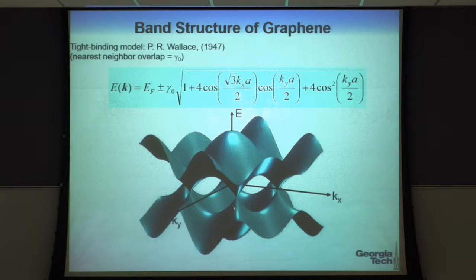And in fact, for graphene, that's where the charge neutrality point is. That is, all the bands are filled up to this point, the Dirac point, and then they're empty above that point. But you can dope graphene. You can put extra electrons in or take electrons out so that the Fermi level could be above or below the Dirac point. But for neutral graphene, it's right at the Dirac point. And these bands, based on the tight binding model, in fact have an analytic form. The important part for much of what we do is down here, right around the Dirac point.